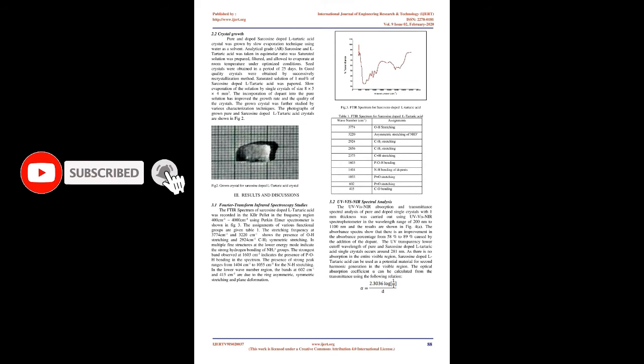3 Results and discussions. 3.1 Fourier transform infrared spectroscopy studies. The FTIR spectrum of sarcosine-doped L-tartaric acid was recorded in a KBr pellet in the frequency region 400 cm⁻¹ to 4000 cm⁻¹ using a Perkin-Elmer spectrometer, as shown in Fig 3. The assignments of various functional groups are given in Table 1. The stretching frequencies at 3774 cm⁻¹ and 3220 cm⁻¹ show the presence of OH stretching, and 2924 cm⁻¹ CH2 symmetric stretching. Multiple fine structures at the lower energy mode indicate the strong hydrogen bonding of NH3+ groups.